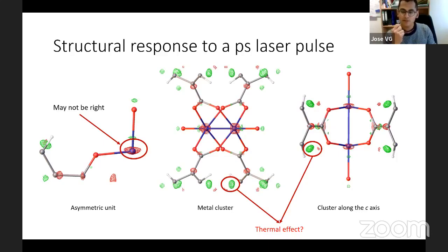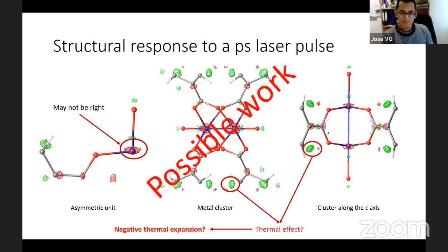However, this could be because, as I say, you introduce more energy than necessary for photoinduced excitation. This may be because of the thermal effect. So this structural change we are seeing in HKUST-1 could be mostly driven by just thermal effects. And what could this be? Possibly a negative thermal expansion. HKUST-1 is very well known to have negative thermal expansion, and probably we are having the same when we just irradiate with light, a structural change similar to what we see at different temperatures. However, as I say, this needs more work, and this would be another possibility for an upcoming student.